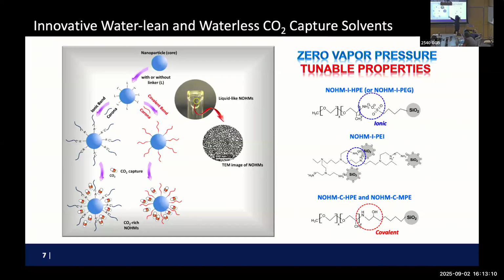And basically he tethered the polymer onto nanoparticles. And the final product was very interesting. Instead of a powder with a coating on it, because we did the right grafting density and it's a short brush, you end up with this liquid-like material. In your bottle, it is still liquid. It flows and all that.